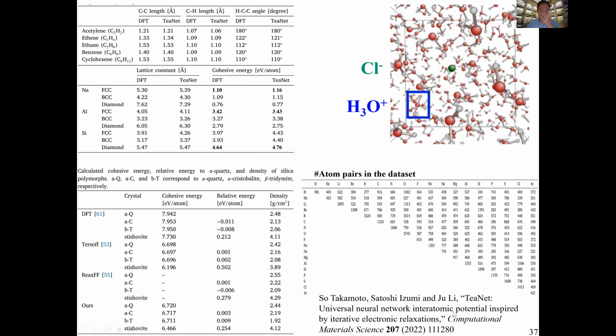So this is what we got when Sō was at MIT. We were able to reproduce hydrocarbons, so acetylene, ethane, benzene, their properties, and then crystalline sodium, aluminum, silicon. And then these are the different polymorphs of SiO2, silica: quartz, alpha quartz, cristobalite, tridymite, and some amorphous silica. This is water. So we have a chloride ion with a solvation shell, and then also a hydronium ion.